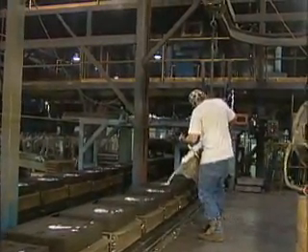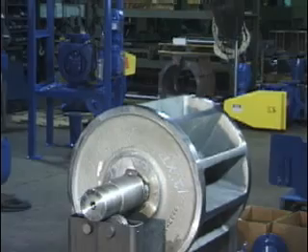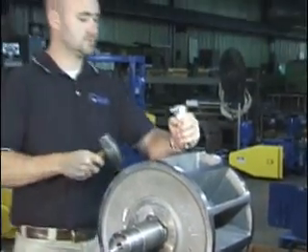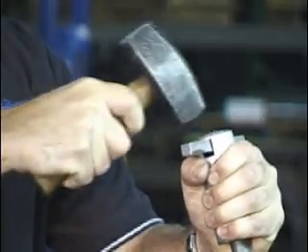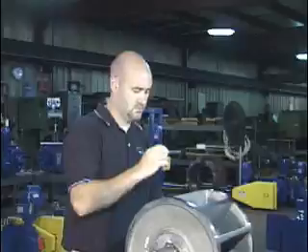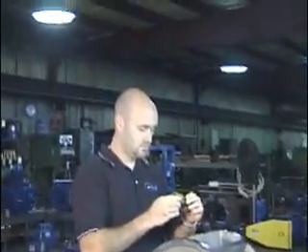Production of a Permaflow Extreme Feeder begins with the receipt of an order. A set of customized drawings is prepared to meet the specifications of the system into which the feeder will be installed. Rough castings are poured at the foundry and shipped to our manufacturing facility. Castings must then pass several thorough quality control inspections, including a hardness test, to ensure that a nominal 550 Brinell hardness is maintained. The castings are then rough ground and re-inspected prior to the finished grind.